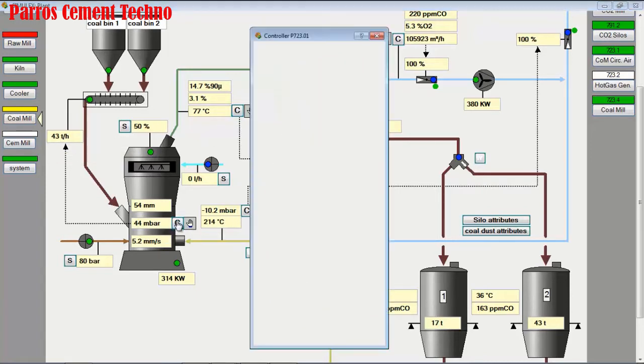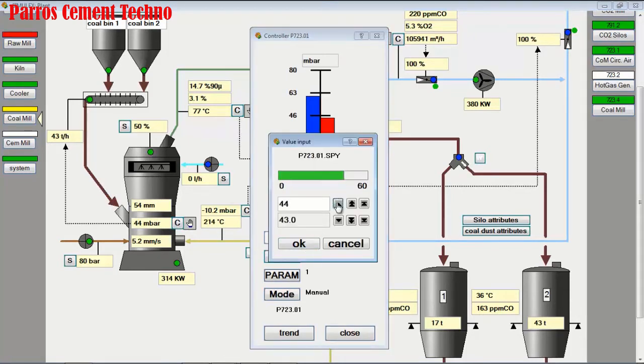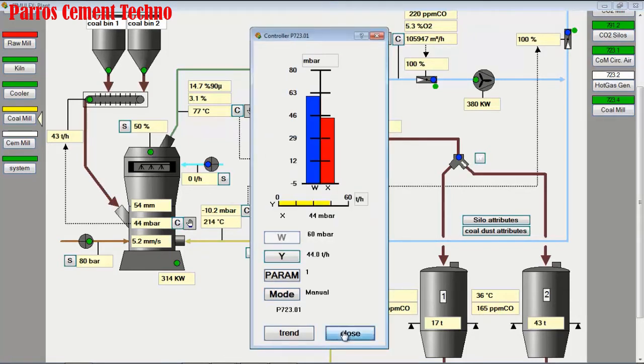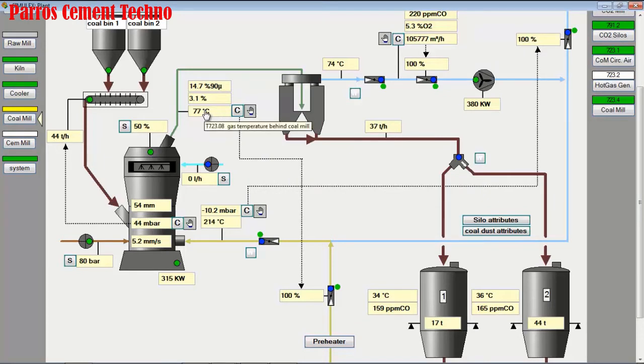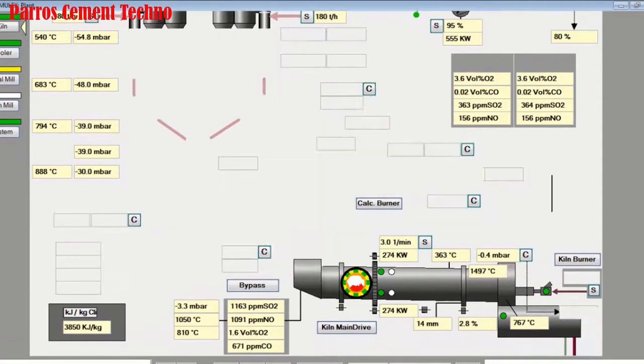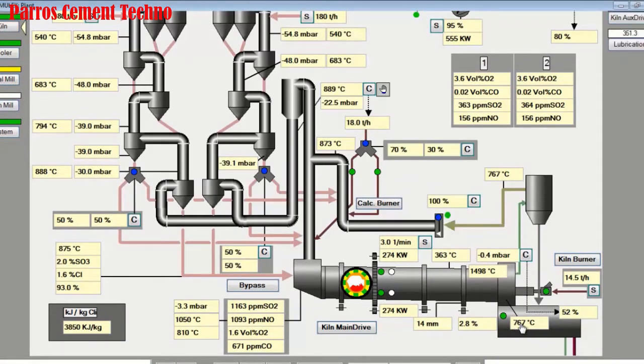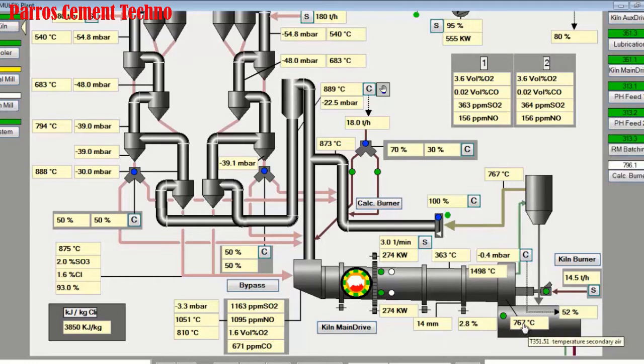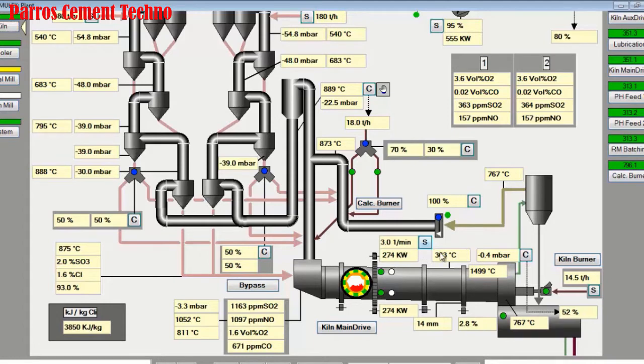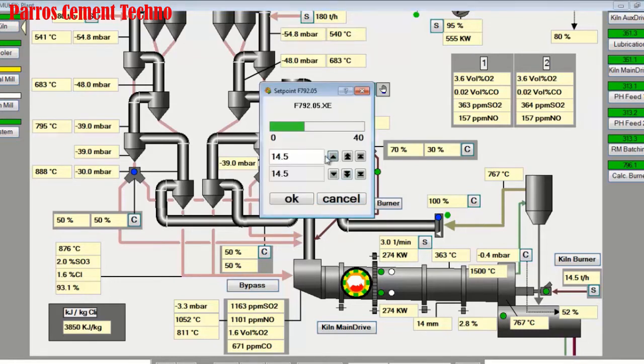Because the mill outlet temperature is still 77 degrees Celsius, we increase the mill feed by 1 ton to 44 tons per hour, as the stock of pulverized coal in the bin is still low. Back at the kiln display monitor, the secondary temperature is still below 800 degrees Celsius, the free lime is still 2.8%, the kiln speed is 3.0 RPM, and the sintering zone temperature is still quite high.